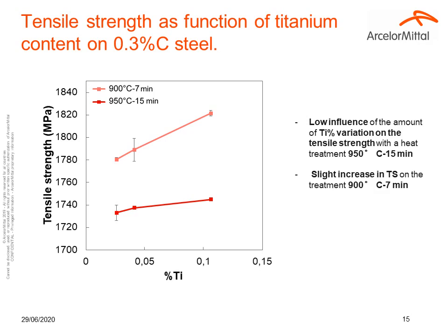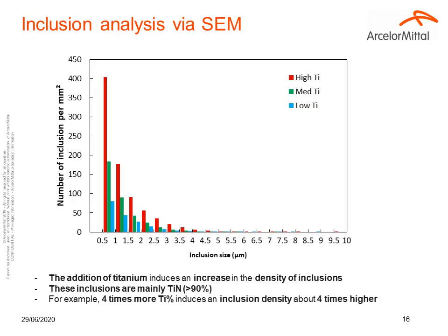An analysis has been done via scanning electron microscope. This analysis was carried out on the 3 steels and it is possible to represent the number of inclusions per millimeter square as a function of their size for the 3 different titanium contents. An addition of titanium induces an increase in the density of inclusions. Furthermore, these inclusions are mainly titanium nitride. The inclusion density is directly correlated to the nominal titanium content. For example, when the amount of titanium is multiplied by 4, the number of inclusions per millimeter square is also multiplied by 4. So the addition of titanium has a little effect on the ultimate tensile strength, but induces more inclusions.